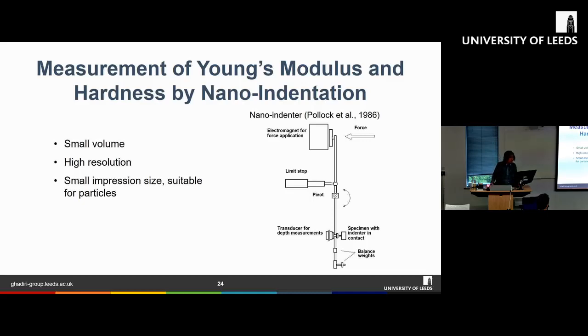So since the late 80s, we have this new development by Pollock, a new indentation method that we call nanoindentation. What's different compared to the previous indentation tests is that we can use much smaller particles, and this type of setup also has higher resolution, meaning that we can do a smaller indentation, but still get enough resolution to look at the force and the change in depth of the indenter during the penetration. Here is an example of the setup of a nanoindenter.